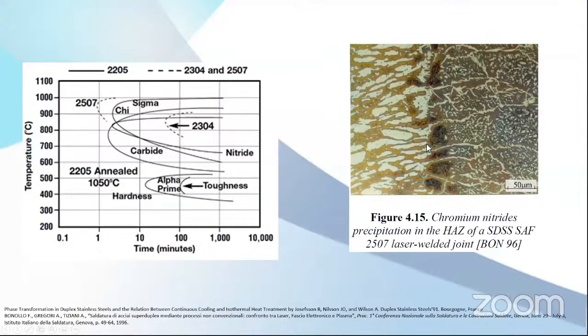And this is what happened with fast cooling of duplex. This is the weldment, the fusion zone, and this is the parent metal. And you can see in the heat affected zones, this is cooling very fast because with laser welding the cooling is very fast compared to arc welding. You can see the chromium nitride precipitation, and this will be the starting point of corrosion.